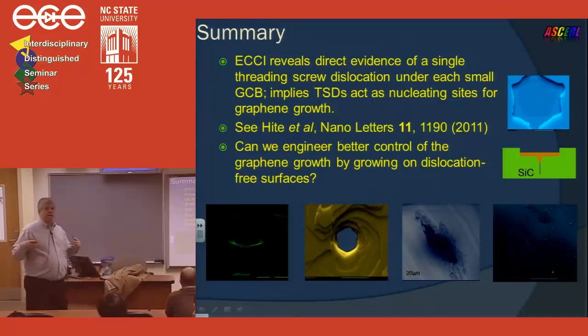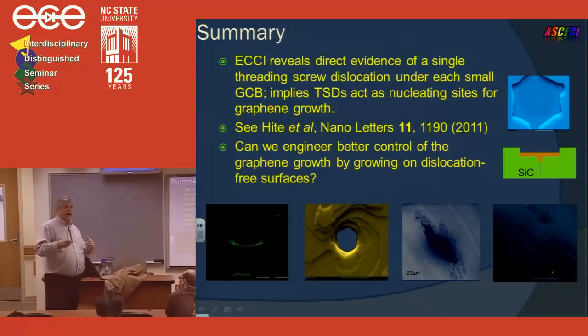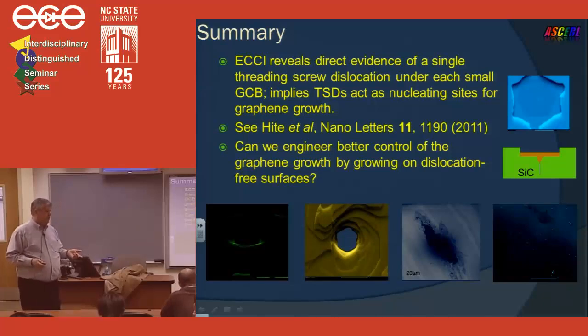Basically, you need to come up with a way of overcoming the screw dislocation nucleation mechanism to be able to grow on the carbon face. Now, if you had a sample with no screw dislocations, then you could, in principle, grow very high-quality graphene. But it's hard to get a bulk material of silicon carbide without a screw dislocation. But there is one way, and we've tested it out.